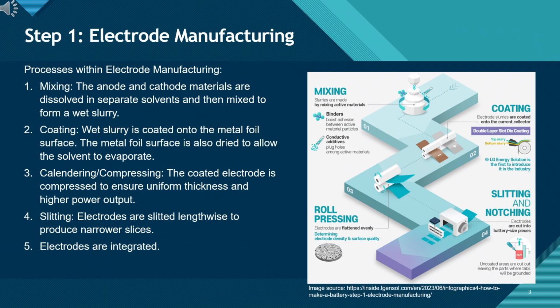Electrode manufacturing is the foundation of battery making, and it includes 5 key processes. First is mixing. Here, anode and cathode powders are dissolved with binders and solvents to create a wet slurry. This step is crucial for ensuring that materials are evenly blended. Second is coating. The slurry is spread onto thin metal foils, copper for the anode and aluminum for the cathode. The coated foils are then dried, allowing the solvent to evaporate.